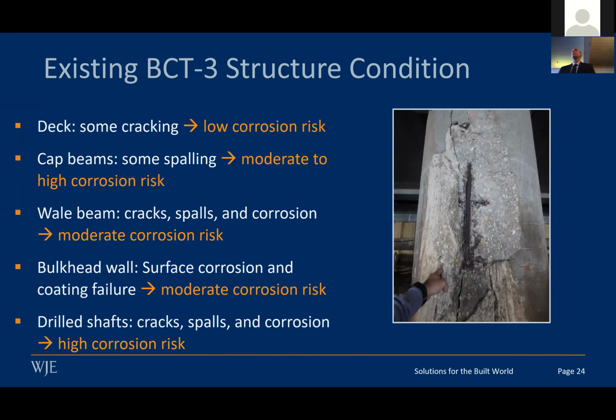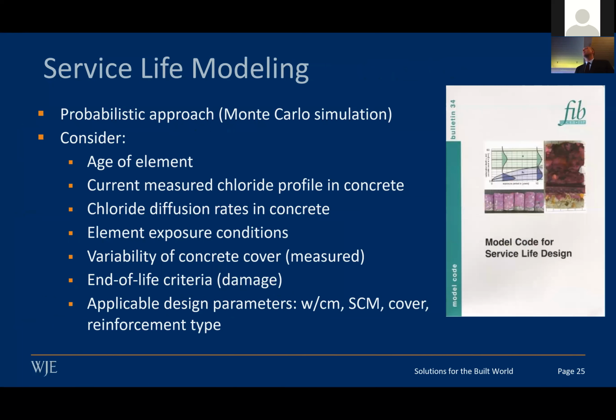And so being able to take those measurements, take those readings, and really do something with it was where the service life modeling came in. This is to help us refine what elements needed the repair and which elements were okay as they were. We used the fib Bulletin 34 for our evaluation of the service life model. It's a probabilistic approach that uses the data you capture in the field, so your cover measurements, your chloride diffusion rates, your chloride profiles, and then extrapolates that to predict the service life.